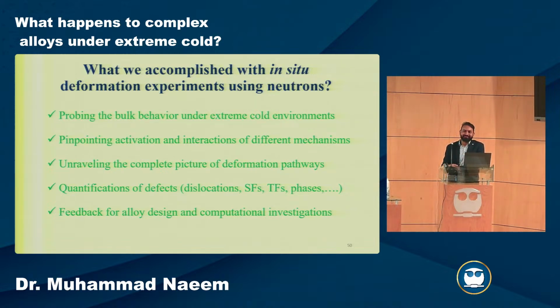That was their argument. But now we have seen the example which I've shown before going into conventional systems, that in this vanadium cobalt nickel there is also just one simple dislocation slip mechanism, but still it increases ductility. But it's not the only one. People were actually working in the 1960s on single crystals. There is a lot of literature on aluminum single crystals, for example, where people saw exactly the same thing. When you go to low temperature, you have higher ductility.